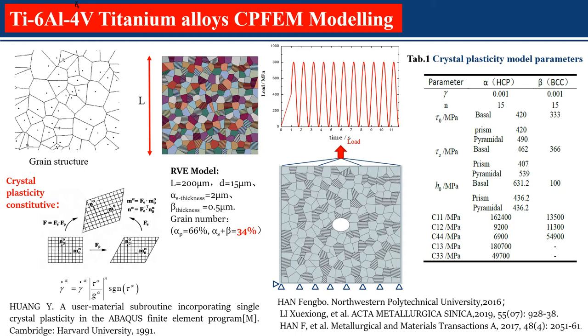A clamped boundary condition is imposed at the bottom. Fatigue loading is applied on the upper edge. The fatigue loading is depicted in the figure we present here. Maximum stress is 800 megapascal, while the stress threshold is zero. And in this work, the crystal plasticity constitutive equation is used from published literature, which has been proved to be very effective in CPFEM modeling of alloys. Parameters adopted in the work are listed in the table, all cited from published literatures.